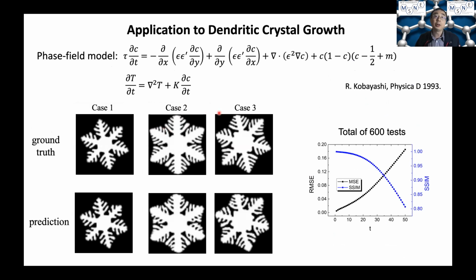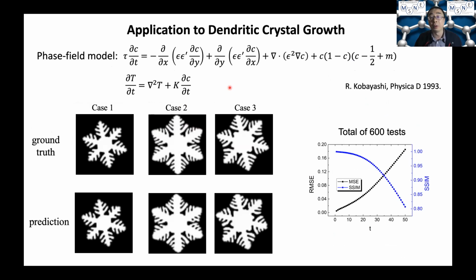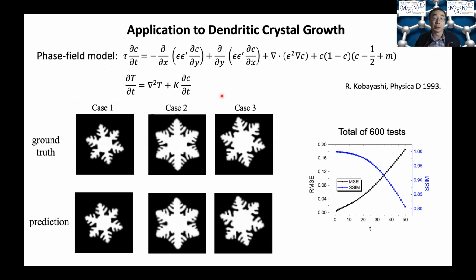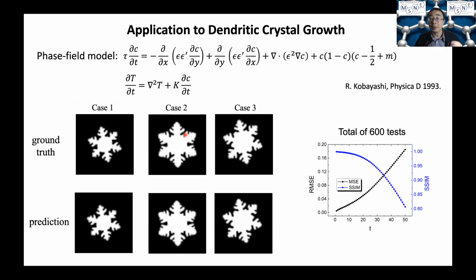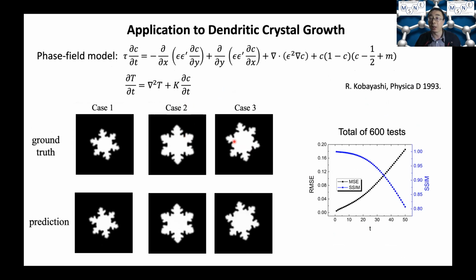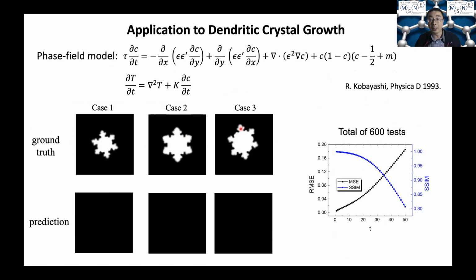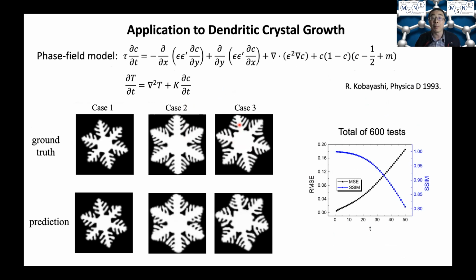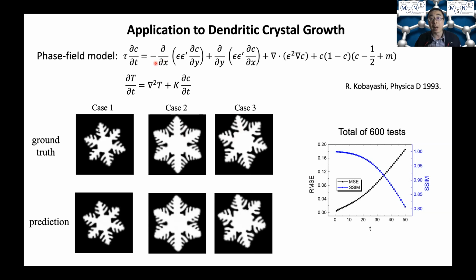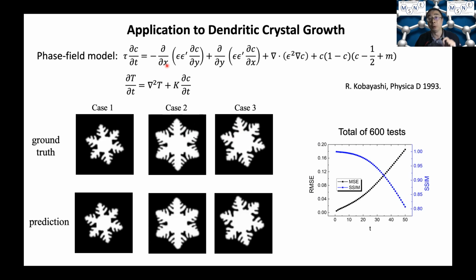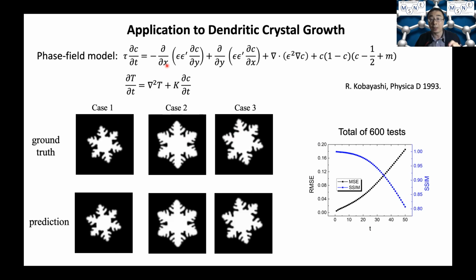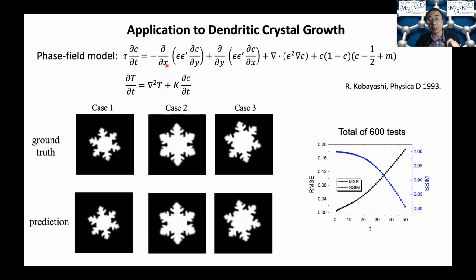And we even challenged the model with a more difficult problem, that is to predict dendrite growth, for example, during solidification process. So we know during dendrite growth, the system is intrinsically unstable. The interface between the solid and liquid phases will develop instability and generate this very intricate, complicated dendritic pattern. So here we use a simple phase field model as a proof of concept to generate the simulation data on the dendrite growth and then train the model on such data.